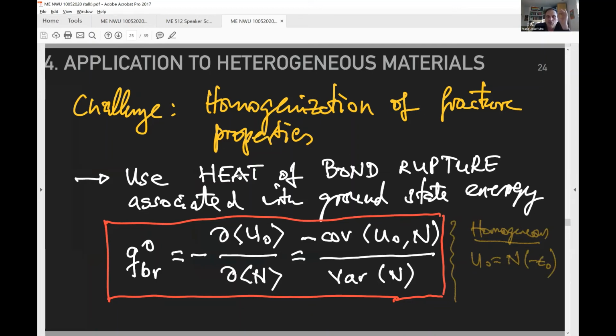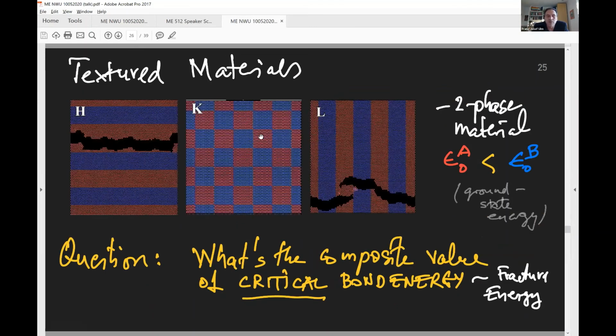And what I'm using here is the heat of bond rupture. You know, the problem of homogenization of fracture properties is that linear averages or quadratic averages don't apply to these quantities. However, now that I have a definition of the heat of bond rupture, which is based upon energy definitions, meaning with this covariance of the ground state energy and the variance, I can apply this directly to heterogeneous materials. And what I want to do here is to show you how that works for a textured material. So a layered material, the other layer, the other way around. I have two materials. One has a ground state energy, epsilon zero A, the red one, which is smaller than the blue one, epsilon zero B.